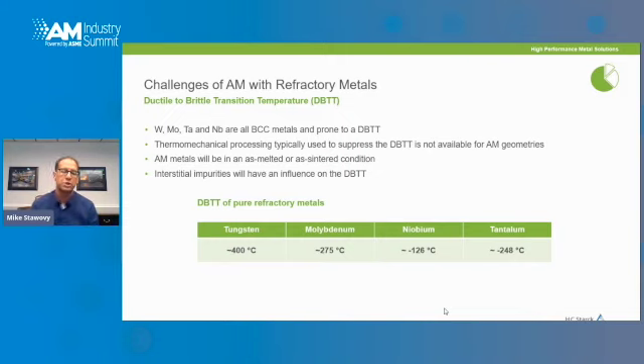And it's the same situation for molybdenum in that fully recrystallized or as laser melted condition. It's going to be quite brittle at room temperature. And with other materials like niobium or tantalum, the ductile brittle transition temperature is below room temperature, so those materials are going to be quite ductile at room temperature in that material condition.